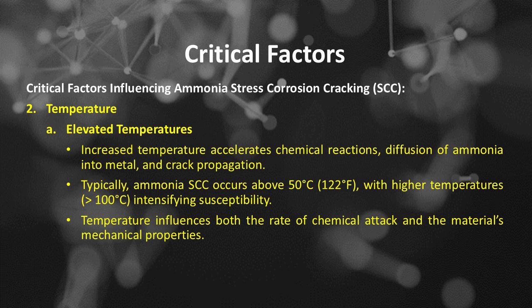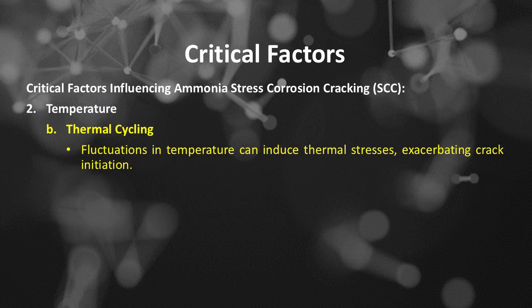Typically, ammonia SCC occurs above 50 degrees Celsius or 122 degrees Fahrenheit, with higher temperatures, greater than 100 degrees Celsius, intensifying susceptibility. Temperature influences both the rate of chemical attack and the material's mechanical properties. Number B, thermal cycling. Fluctuations in temperature can induce thermal stresses, exacerbating crack initiation.